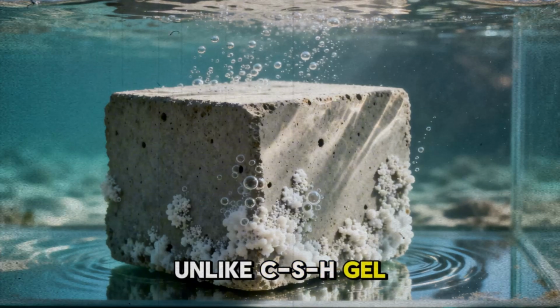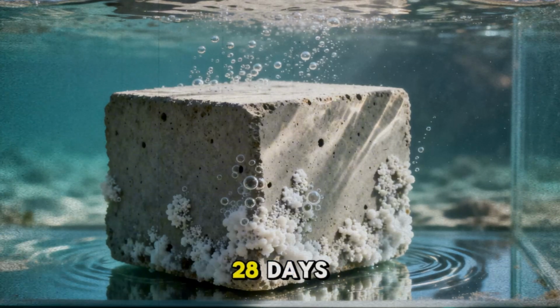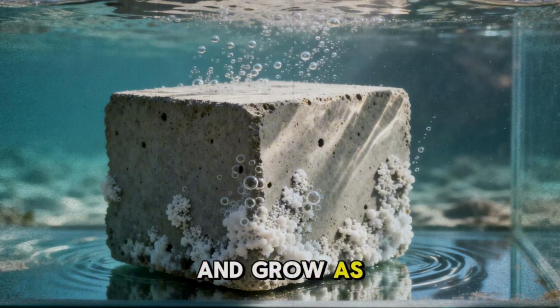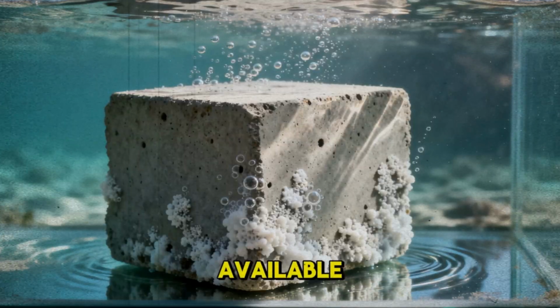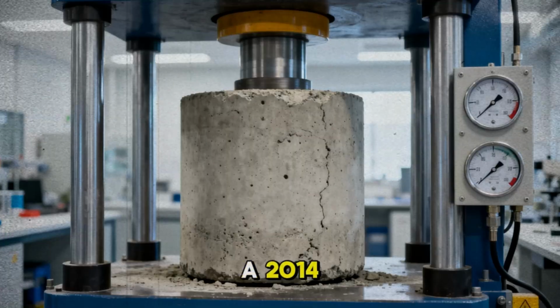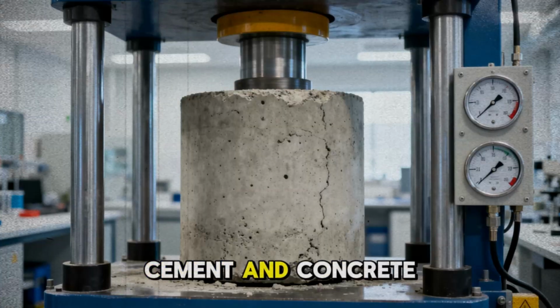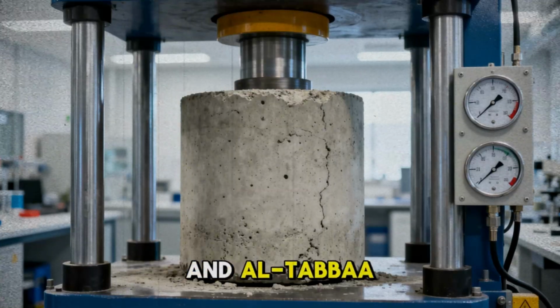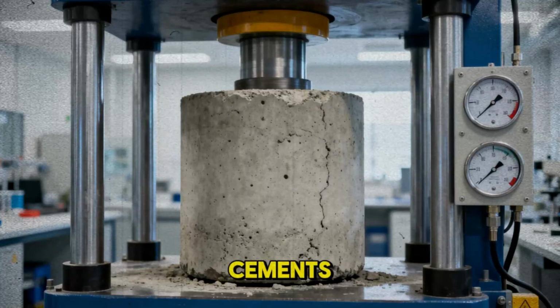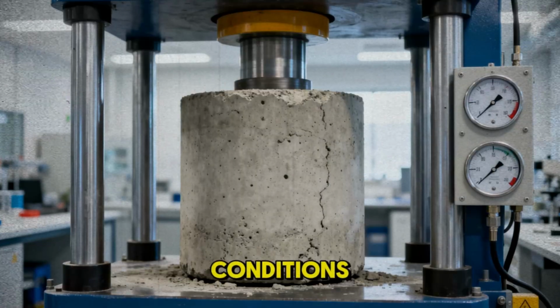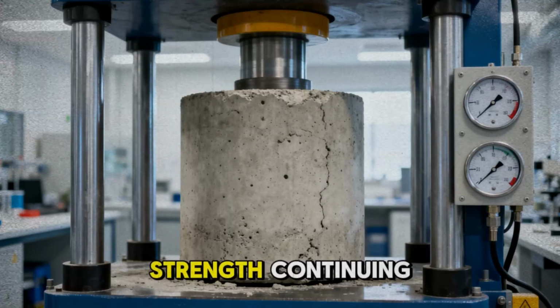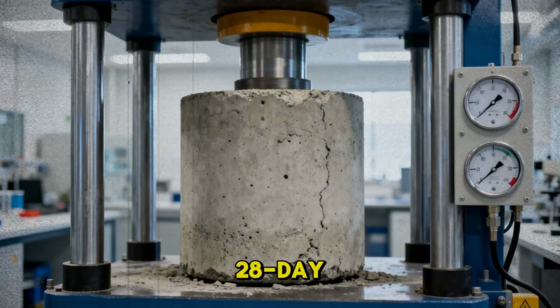Unlike CSH gel, these crystals do not plateau at 28 days. They continue to nucleate and grow as long as CO₂ and mineral ions are available. Cited Study 1. A 2014 paper published in Cement and Concrete Research by Unluer and Al-Tabbaa examined reactive magnesia cements cured under CO₂-rich conditions. Their results showed compressive strength continuing to increase well beyond the 28-day benchmark.